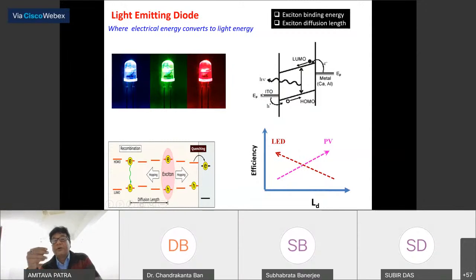But the important aspects for light emitting devices or photovoltaic cells are that exciton binding energy is very important, and exciton diffusion length is very important, because you generate electron and hole. When you excite a system with light, they can generate electron and hole. So they will recombine and generate light. So in the case of a light emitting diode, the recombination of electron and hole is very important. That's why the diffusion length should be less. But in the case of a solar cell, you want to separate the electron and hole to generate electrical current. That's why diffusion length should be high and exciton binding energy should be less. So these are the important criteria.